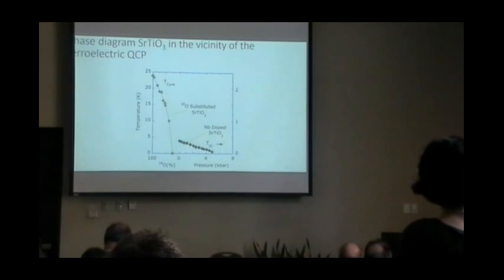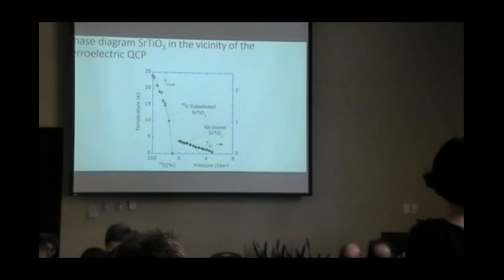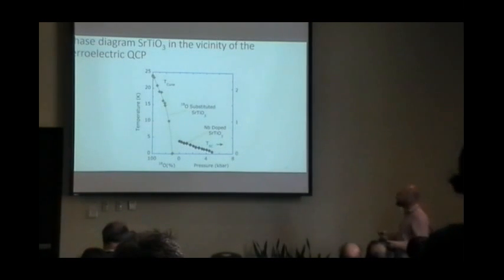So that was a negative pressure because, as I know, usually by increasing the pressure, the TC increases. Yeah, if you have a classical BCS superconductor, this is what you would expect. In this case, we related it to the quantum critical point, which is one of the reasons why you suppress it so heavily. Far away from the quantum critical point, you don't have the soft transverse optical phonon modes, and thus you wouldn't expect to have any superconductivity of that type.